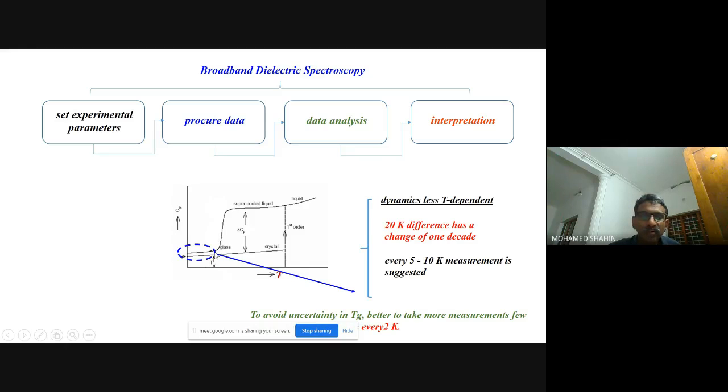Okay, so below that you ensure that some 10 temperatures are here. Then you will be in a good position to present your data to anyone. Then it happens that in the supercooled region, we know that it is thermodynamically not stable. Then all of a sudden it crystallizes, gradually it crystallizes, and you see that it is becoming crystal somewhere here. So you don't get data in between.